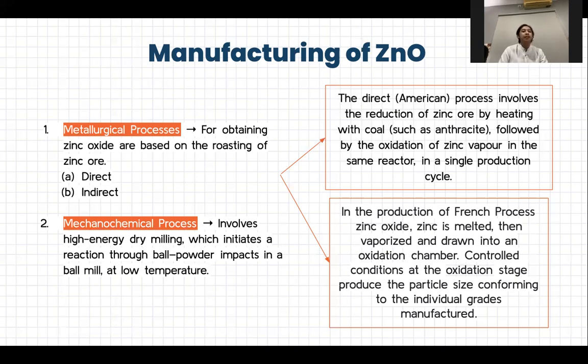The resulting product is zinc oxide that contains impurities in the form of compounds of other metals from the zinc ore, and the ZnO particles are mainly needle shaped and sometimes spherical. To obtain a product with a permanent white color, the oxides of lead, iron, and cadmium that are present are converted to sulfates, increasing the permanence of the color, but also increasing the content of water soluble substances and increasing the acidity of the product.